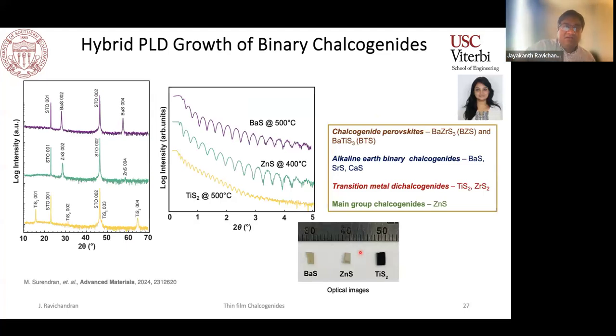In this case, we took a step back and thought about whether we can grow a variety of different chalcogenides. So we said we're going to give it a shot with the chalcogenide perovskites. We have been interested in BaZrS3, BaTiS3, but we'll also start looking at some of the binary simpler chalcogenides, such as the alkaline earth chalcogenides like barium sulfide, strontium sulfide, calcium sulfide, main group chalcogenides such as zinc sulfide, and transition metal chalcogenides such as titanium sulfide and zirconium sulfide. And I show a select few where we do get textured growth. I'm showing barium sulfide, which represents the alkaline earth metals, zinc sulfide for the main group, and titanium sulfide for the transition metals. In all these cases, you can grow at relatively benign temperatures.